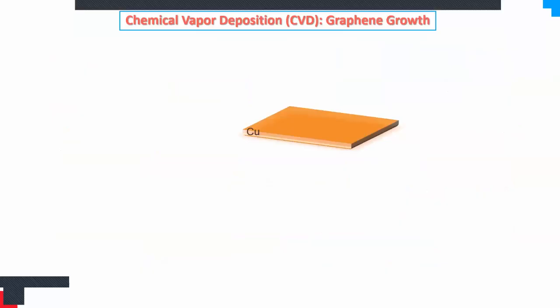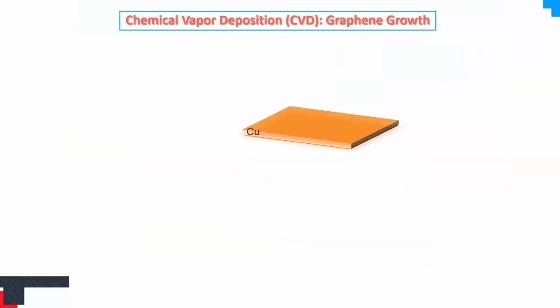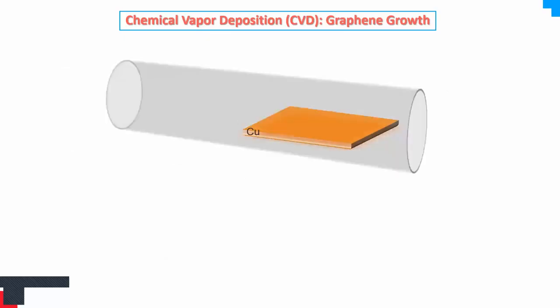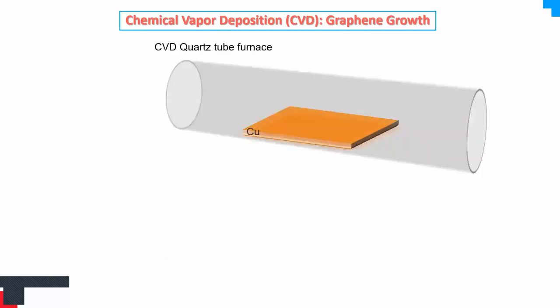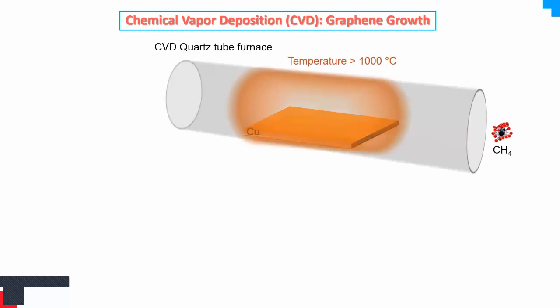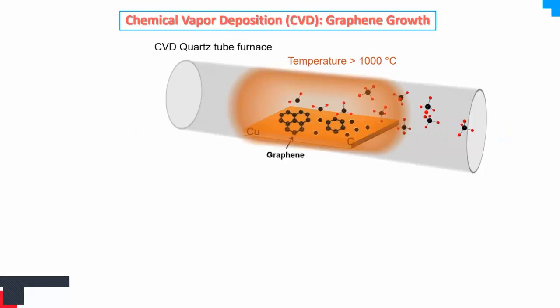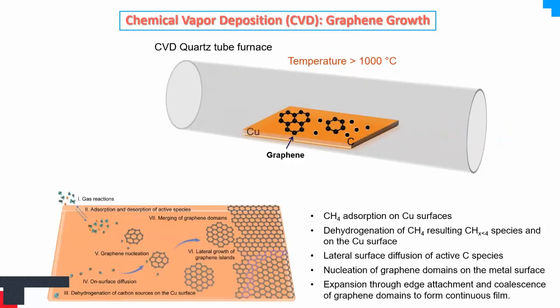So this is a very simple schematic to show how chemical vapor deposition works for the growth of graphene. Normally you have a catalyst, which here is copper. It could be nickel or other metals. You put it in a CVD furnace, a CVD tube, at high temperature, and then some precursors come in, like the methane gas you see here. You can use acetylene or other carbon precursors. Those precursors dissociate at high temperature on the surface of the copper catalyst, and ultimately give you a layer of graphene, which is basically an sp2 bonded carbon sheet.